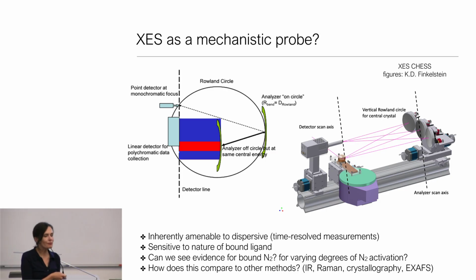But we also had the interest that you could use X-ray emission spectroscopy in a dispersive mode. And this is something that's now being widely done, but at the time, this was my little drawing of what we could do, that we could go from a point focus to our detector. We could just move off the Rowland circle, and we would end up dispersing a range of energies. We just need to replace our point detector with some sort of linear or CCD detector. And so this was something we were interested in doing because we thought that this could be a way to